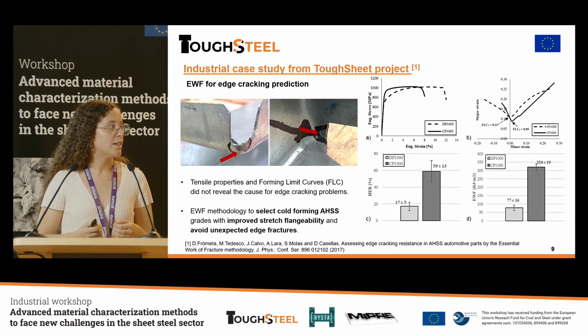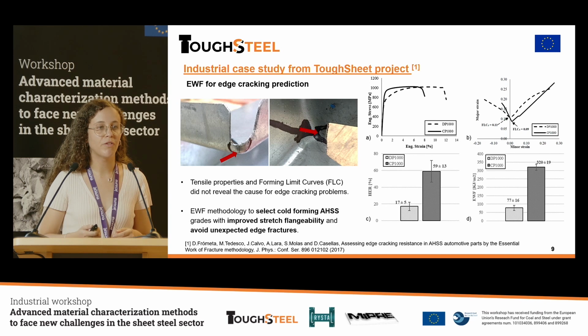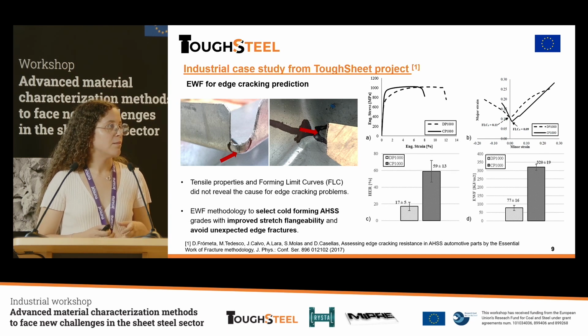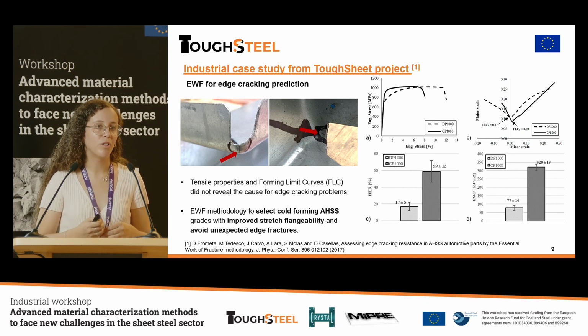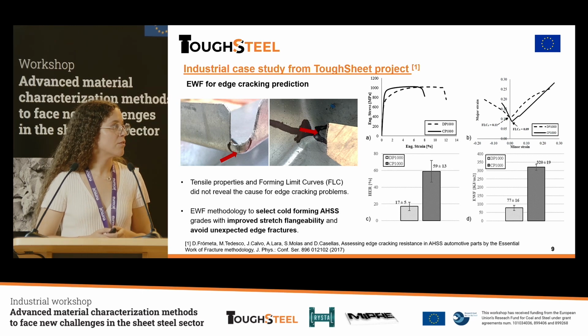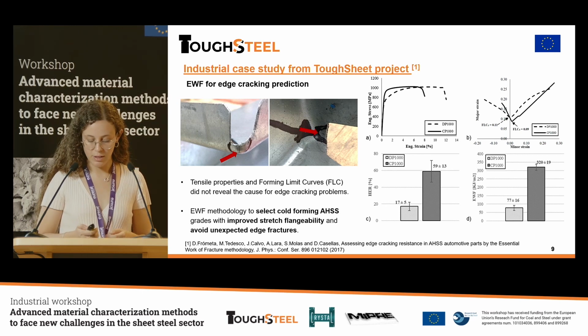Then we performed the hole expansion and also essential work of fracture tests, and we could find a huge difference in the essential work of fracture values for CP1000, and this could better explain why we had this fracture behavior during cold forming in this material. So this would be another application for edge cracking prediction, the use of essential work of fracture.